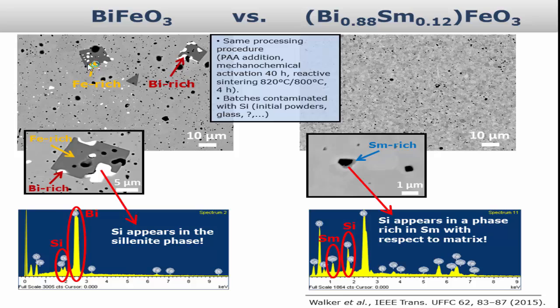While in the case of samarium-modified BiFeO3, we found this same silica in the samarium-rich phase. So you see that once introducing samarium, it uptakes silica and changes completely the phase relations, and this is how the problem of silica somehow disappears in other systems. That's generally related with phase relations and phase diagrams.